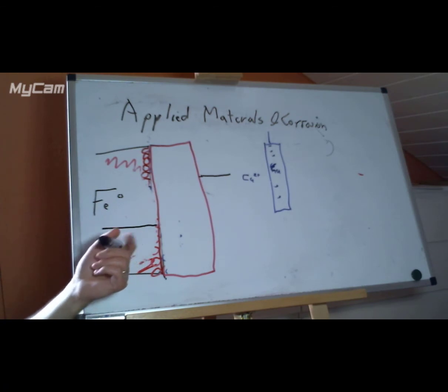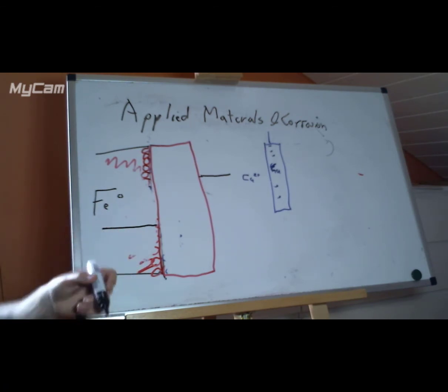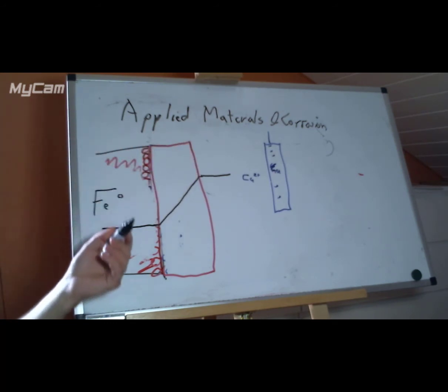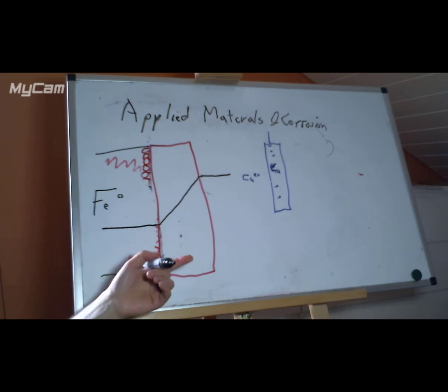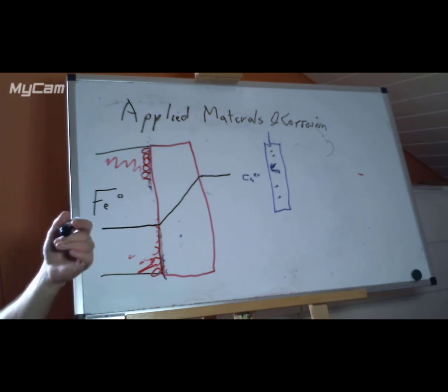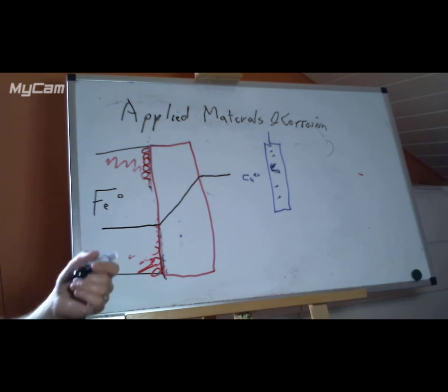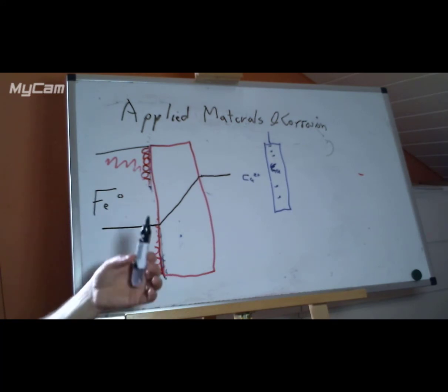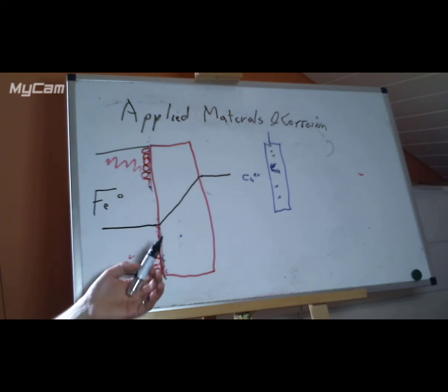And so those ions that were on the surface and on the inside can't get through very easily, and so we would expect there to be some kind of change. If we heat up our non-conductor, then we would expect it to behave like a normal non-conductor. So if we've got a conductor and we heat it up, it gets more resistive because electrons can't move so easily. They're kind of being hit into atoms and they're not going in the right way. But if we're in a non-conductor, then we increase the conductivity, or we reduce the resistivity if we heat it up. The practical part of this would be the ionic resistivity.